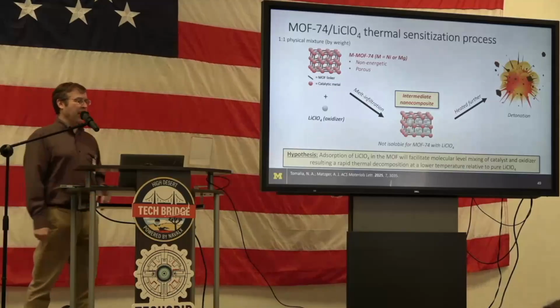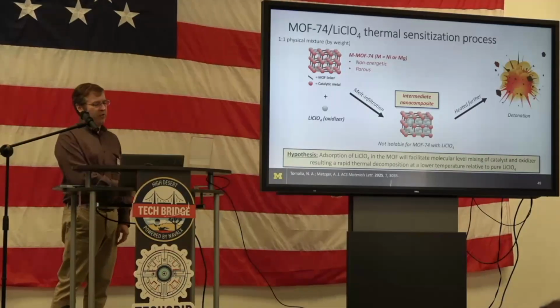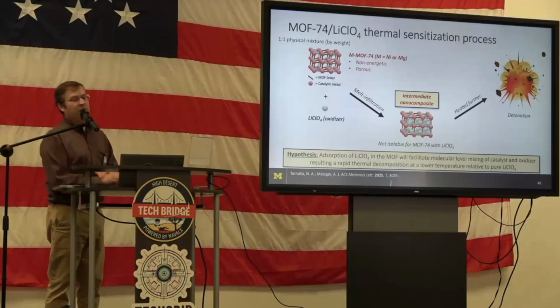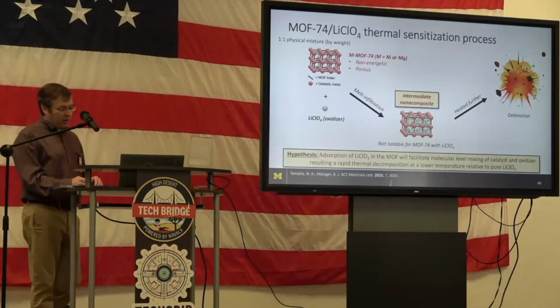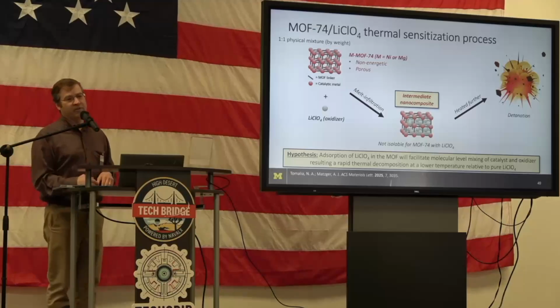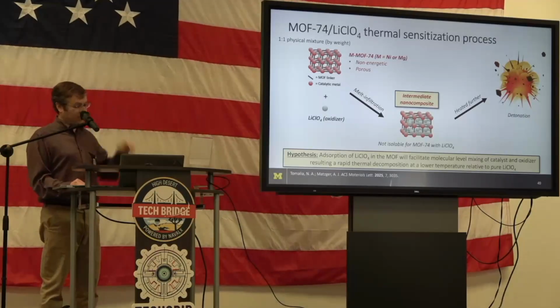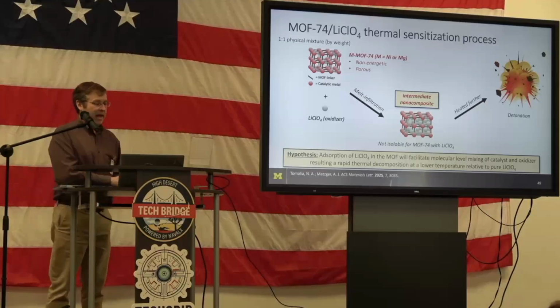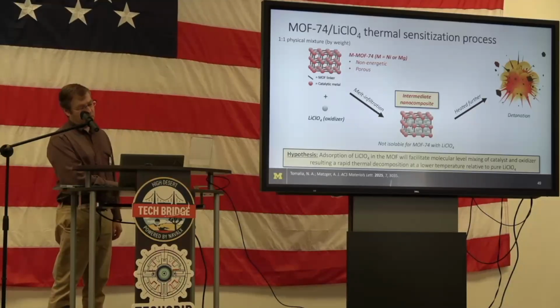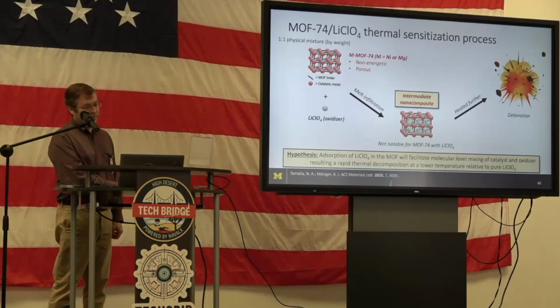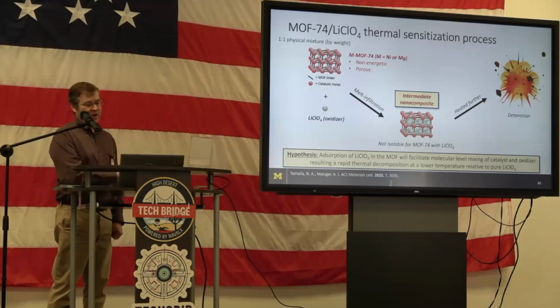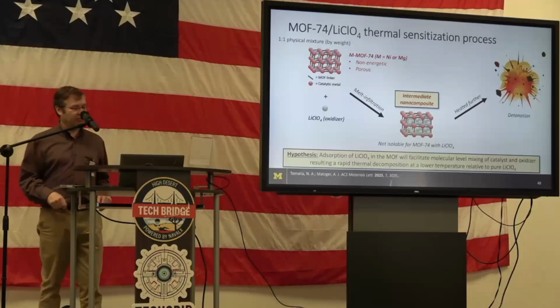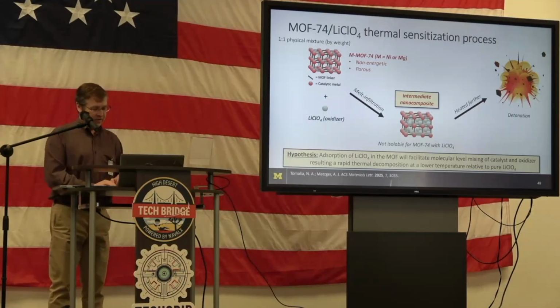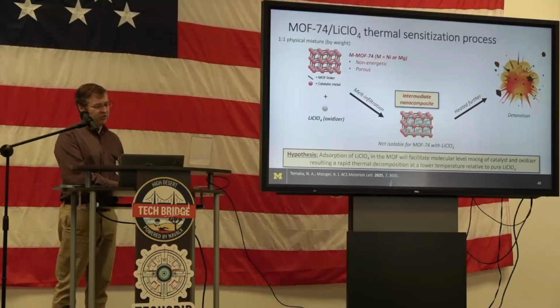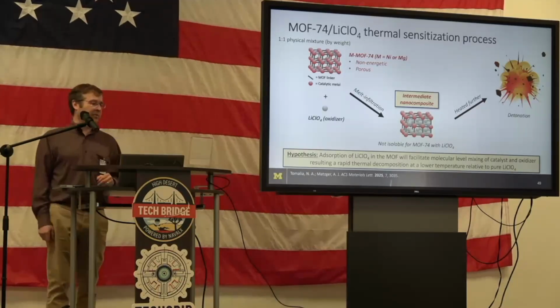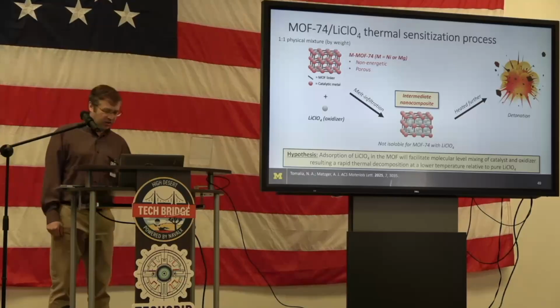All right, so the system I'm going to tell you about uses a MOF called MOF 74. We'll talk a little bit more about that in a second. And we're going to use lithium perchlorate. Why lithium perchlorate? Because it's got a superb oxygen balance, plus 60% oxygen balance. And so then we're going to melt-infiltrate this, and we're going to use the organic linker as the fuel for this oxidizer, and then get this thing hopefully to detonate. The idea was also to pick the metal judiciously, something that could catalyze perchlorate decomposition, because while lithium perchlorate oxidizes, it does so at about 500 degrees.